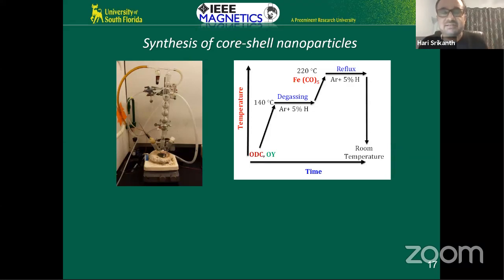So the most important aspect is it's more like an art. Some postdocs, some students are really good at it, and they can actually experiment and come up with their own recipes of making high quality magnetic nanoparticles. Okay. The main thing here is the reaction time, the reaction temperature, and also the surfactants that you use to arrest the growth. And that controls the particle size as well as the shape. Okay. So this is what we do.